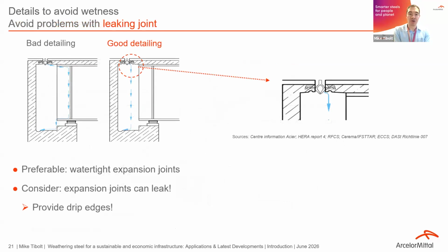Also, the leakage joint should be considered. At the end of the bridge, you have this joint, and the water should not drip on the beam, because anyway it will accumulate, then loose rust particles and lead to staining. So you should apply a dripping nose as shown in the picture, with good detailing, so that the water drips off before getting into contact with the steel beam.